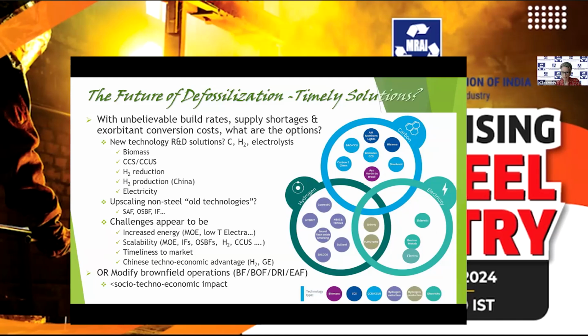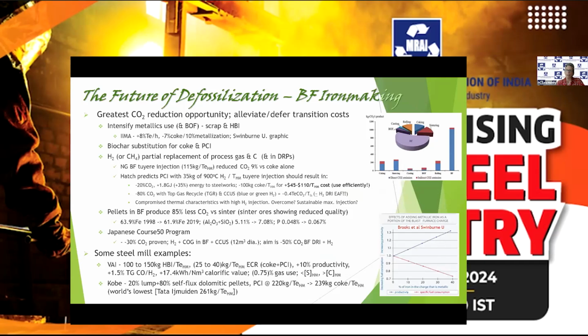The challenges are increased energy, the scalability, which is a big problem, timeliness to market, and we've got an issue with the Chinese techno-economic advantage for hydrogen and green energy. But we could also look at modifying our brownfield operations, which would be less impactful for the socioeconomic issues. The blast furnace ironmaking, we talked about best available technologies. We could intensify the metallics use, which would particularly mean scrap and HBI into the blast furnace. They've seen reduction in coke, and they've increased productivity. We could look at biochar substitution for the coke and PCI, and hydrogen partial replacement of the natural gas or the hot blast to the furnace.